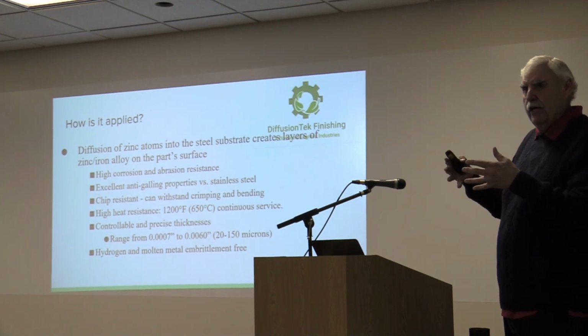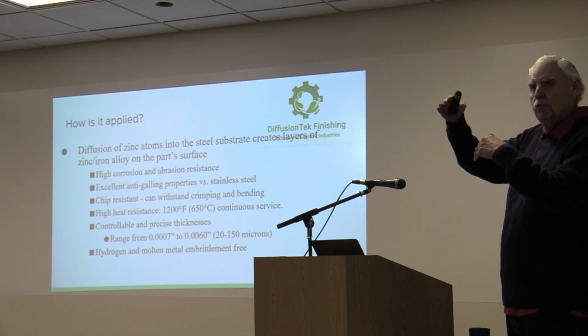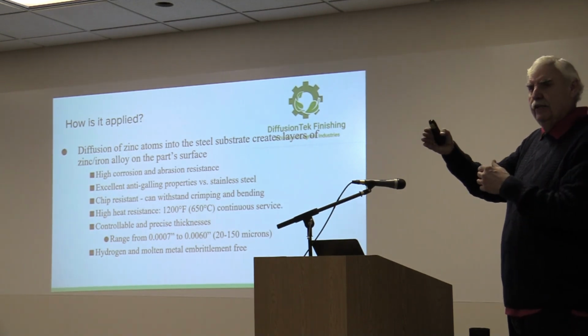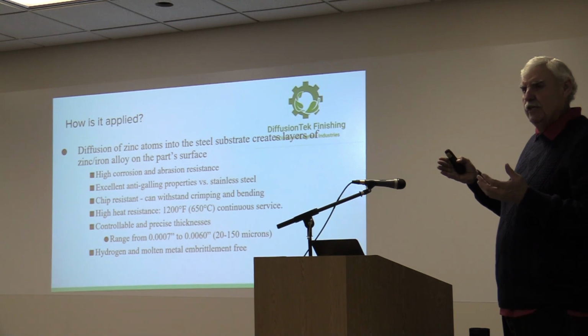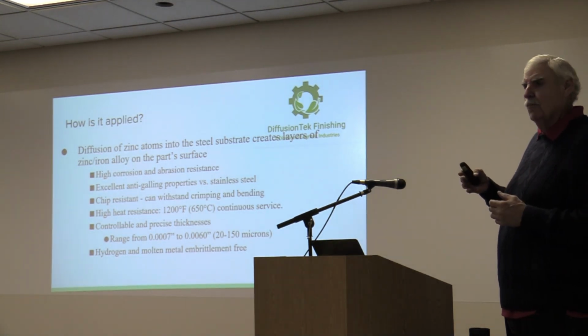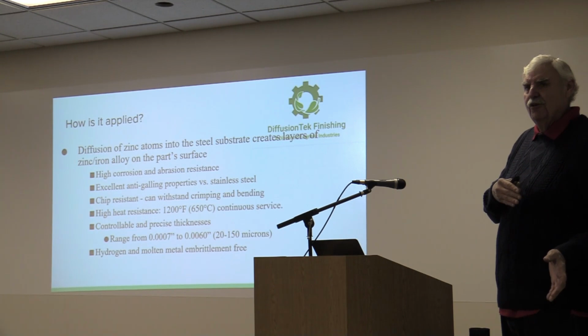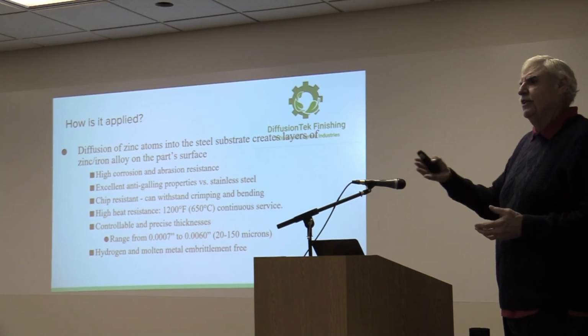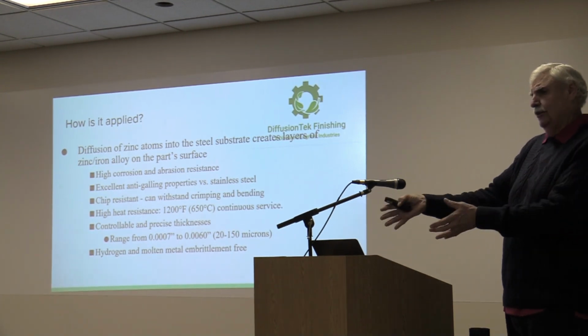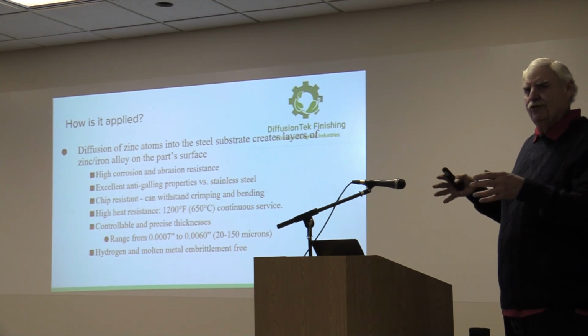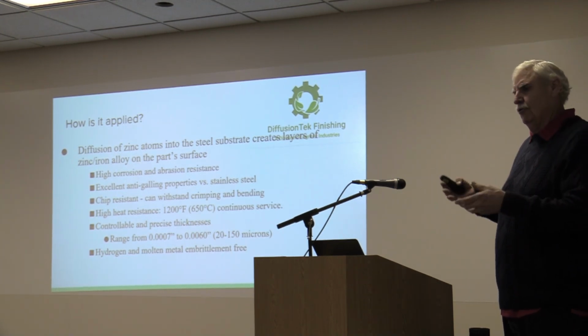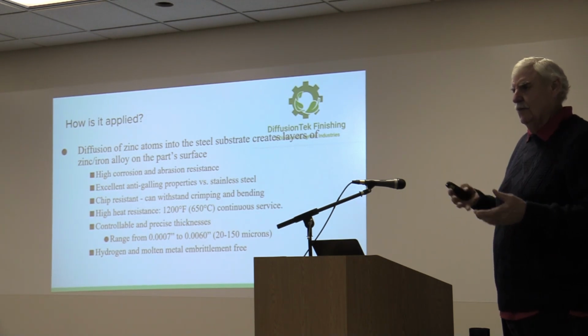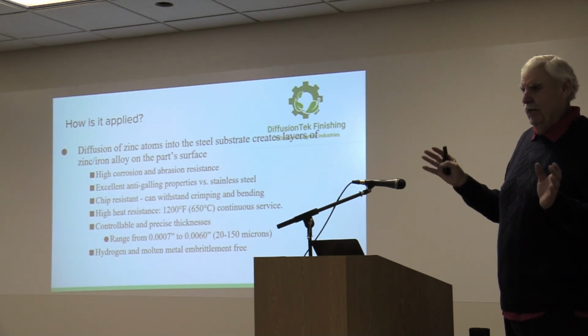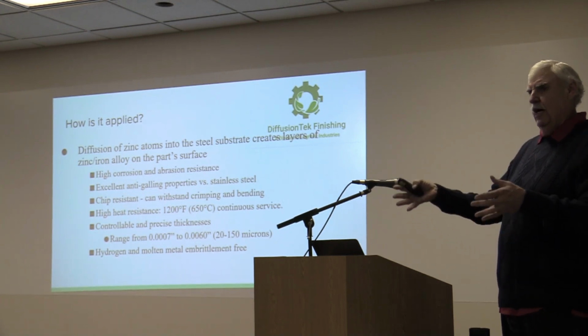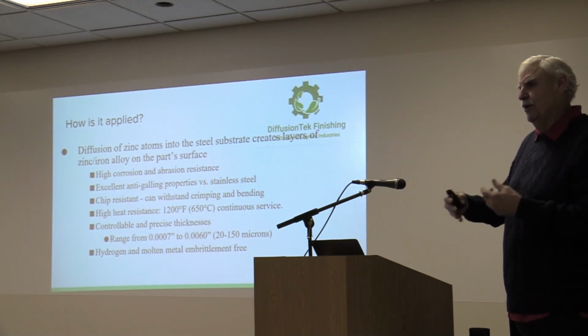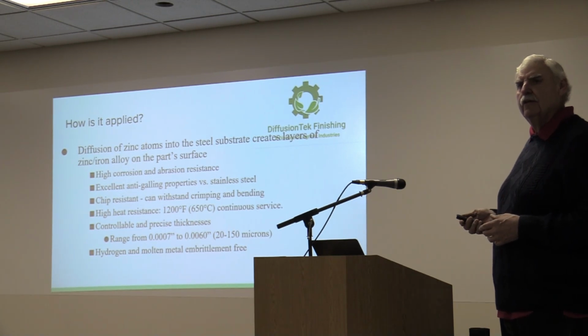And so when you look at the metallurgy, and I'll show you, there are multiple phases. The outermost phase has about 7% iron particulate in it, iron atoms. That's why we use a sealer on top of it, because you would get what we call blushing, and you'd say, oh my gosh, it's corroding. Well, it's that small amount of iron particulate that actually starts to blush. It isn't the substrate that's corroding at all, but if a customer looked at it, they'd say, oh my God, it's corroding. So we use a sealer that we developed on top of it as well.